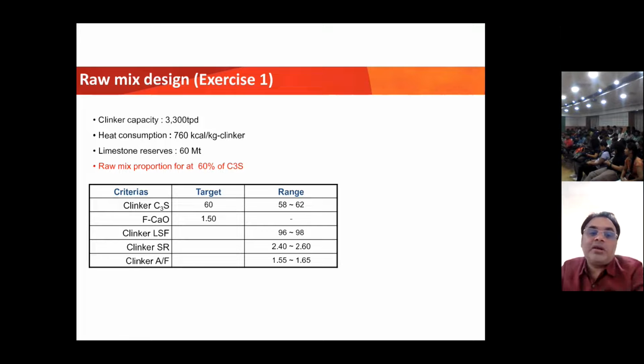This is the proportions of your clinker capacity. Clinker C3S is given, and it is always in the range of around 58 to 62. If it is on the lower side, then your clinker has very little strength, and finally your cement will have less strength. For making your clinker C3S in the range of 58 to 62, you need the LSF between 96 and 98, and similarly the silica ratio of 2.4 to 2.6 is the given range. All these important parameters, like your LSF, silica ratio, and A upon F, that is the alumina modulus, have ranges that are used to get your clinker with C3S of 58 to 62 percent.